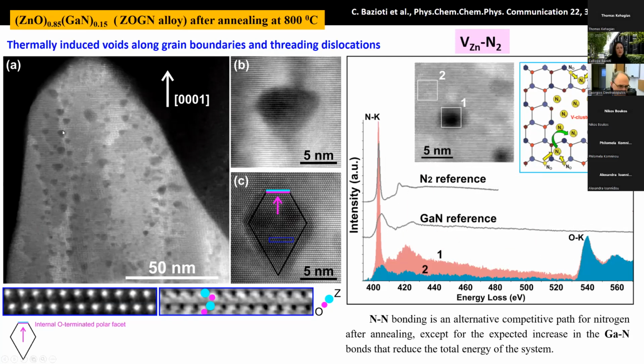Now, to cut the long story short, after annealing, exactly the same phenomenon was observed. You can see here an image of a part of the thin film, and we observed along the grain boundaries and threading dislocations the formation of these nano-sized voids. You can also see here that the larger ones were taking a very faceted shape. And with EELS spectroscopy, again, we proved that these nanovoids were trapping molecular nitrogen, while nitrogen and gallium bonds, as you can see here in the changes in the shapes of EELS spectra, were detected in the rest of the film.